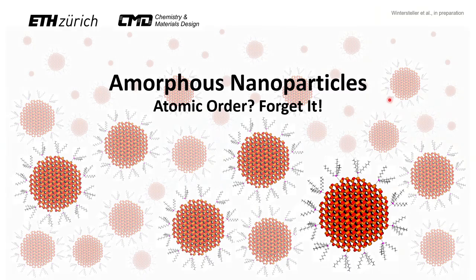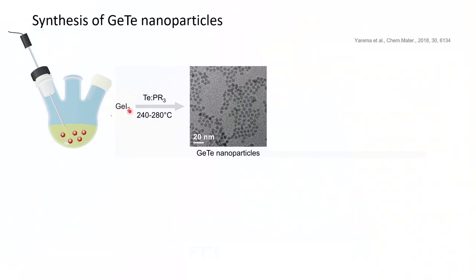Now, this is my last chapter for today. It's about amorphous nanoparticles, and the story there is these are nanoparticles which actually have no atomic order in the initial state. So the story is like that. We mix germanium iodide in the flask with the tellurium from the funnel, and then these are the nanoparticles which we obtain. They look normal, they look like a regular shape, and they look okay, small.